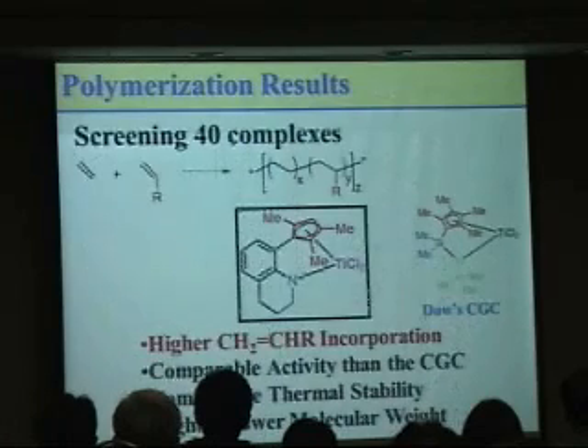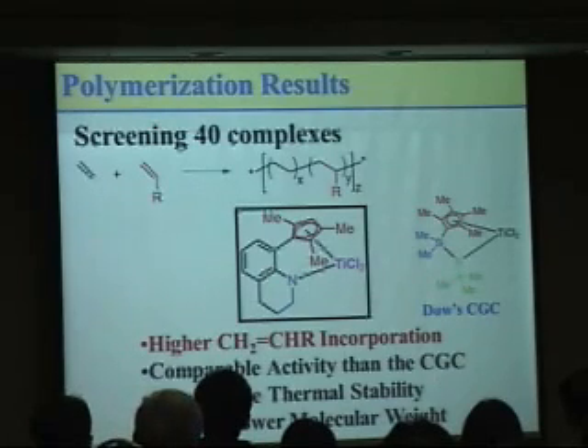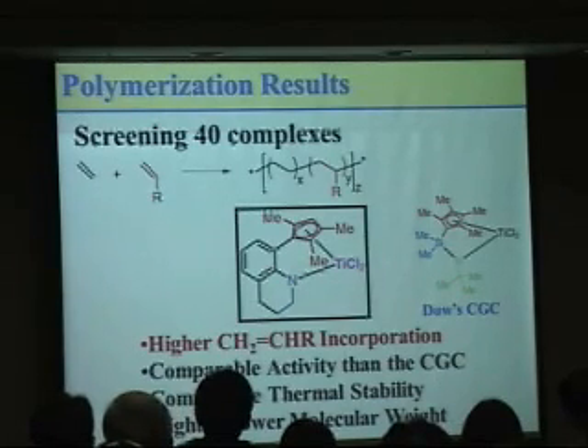Using the route, I was able to prepare a bunch of catalysts, more than 40 new complexes, and I screened them in ethylene α-olefin copolymerizations, and this catalyst turned out to be the best. The catalytic performance in terms of α-olefin incorporation, activity, thermal stability, and molecular weight was not behind the Dow CGC.